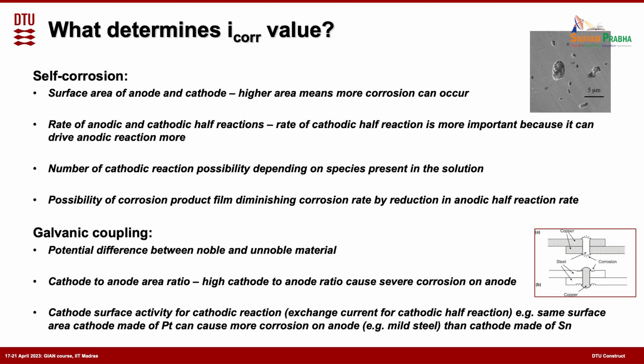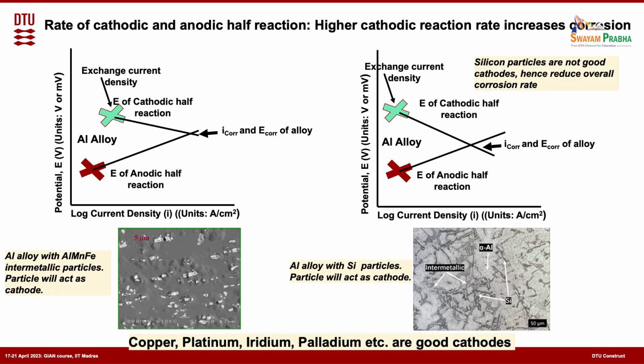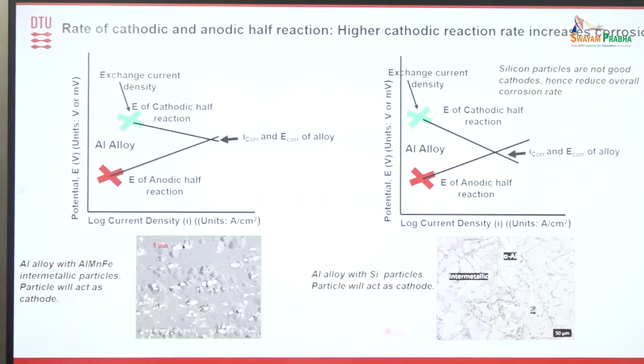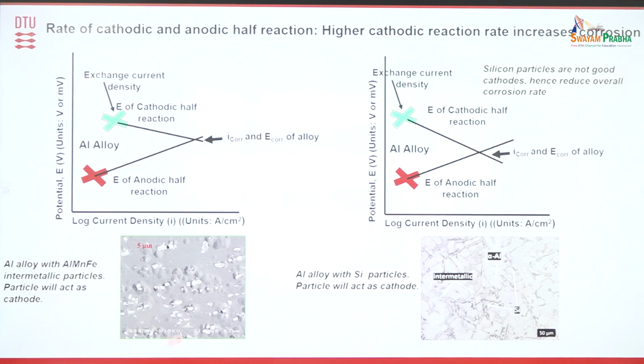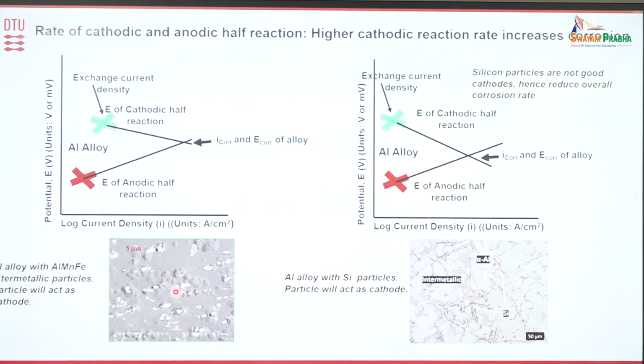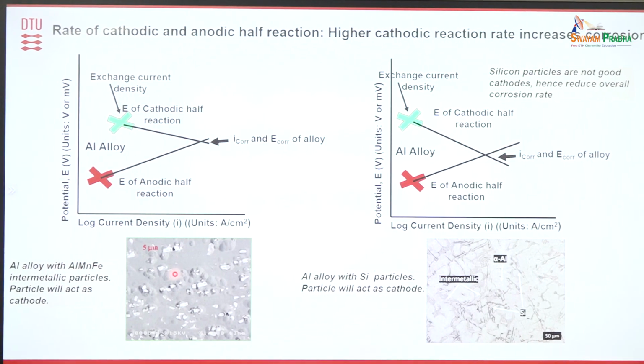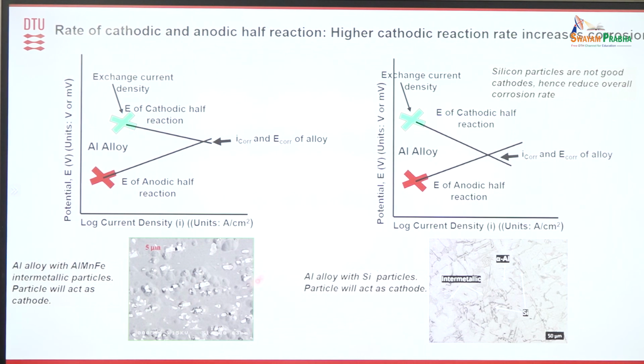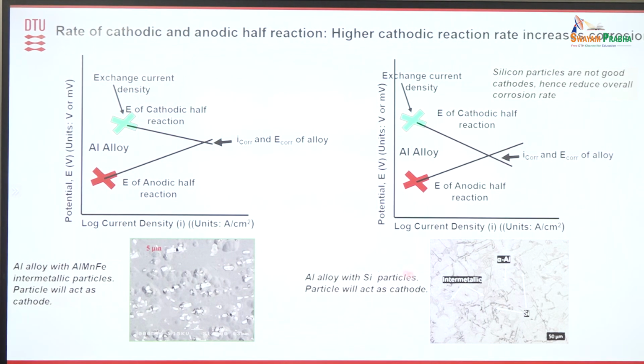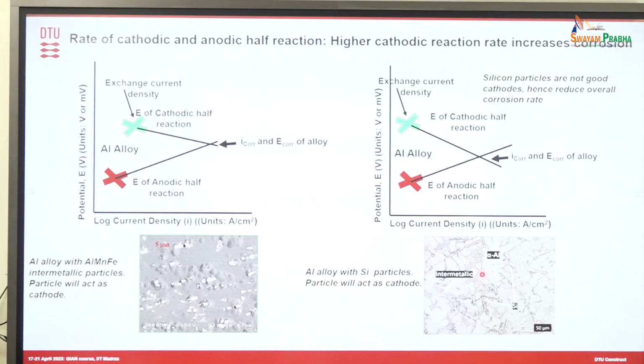Galvanic coupling, I don't think that's that important today, but the cathode to anode area ratio and exchange current density are important, and all those things he mentioned, right? But I think there is also a figure coming to that. So I want to focus a little bit on that exchange current density, because you can see the aluminum alloy here. You have this iron containing intermetallic particle. This is a type of aluminum manganese iron intermetallic particle, and you also see aluminum with silicon particles in it.